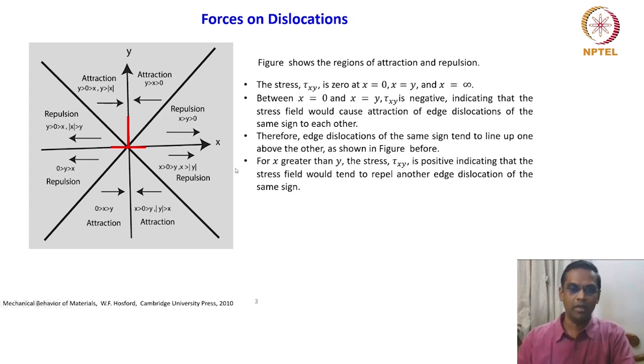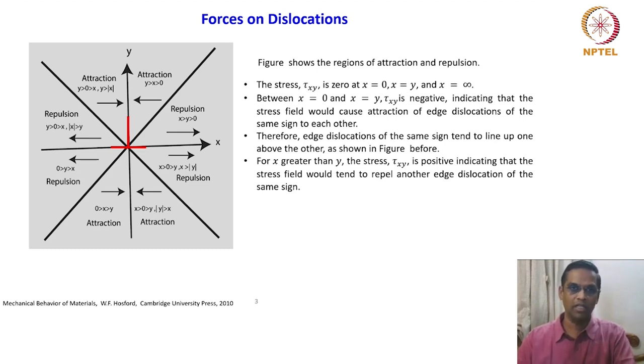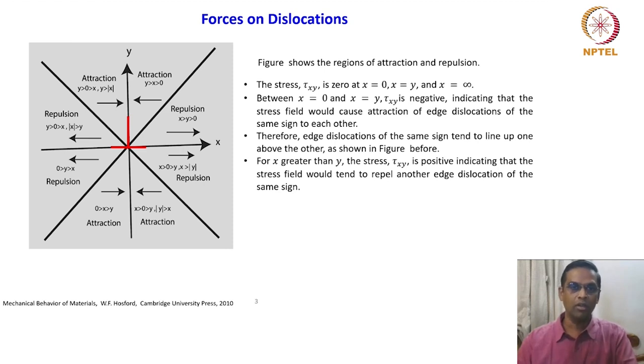The shear components are related to distortion of the bond, while the hydrostatic or normal stresses are related to dilation. In the case of screw dislocations, we can talk about only distortion energy. On the other hand, for edge dislocations, you have both dilation as well as distortion. With this background, it is easy to understand and move forward with solid solution strengthening.